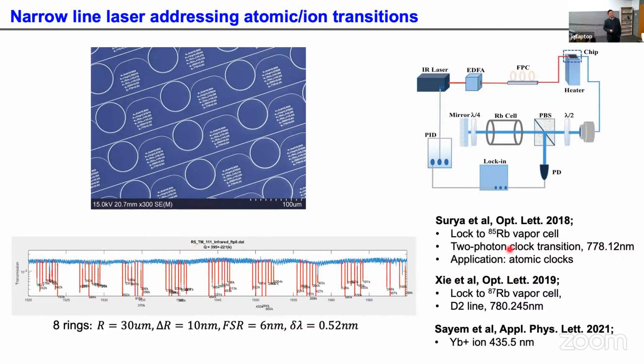One of the challenges in addressing these specific transitions is that you need to tune your resonator to exact wavelengths. Because those are resonant and Doppler-free, the phase matching window is pretty narrow, so you have to use device multiplexing. We have a device that has 16 resonators on a single pair of waveguides, so you have 16 resonances within a free spectral range. Here, the example I'm showing has 8 resonators on the pair of waveguides, so you have 8 resonances, and you can control each resonance very precisely. Each of these rings only varies in dimension by about 10 nanometers, either in radius or width, and you can hit the atomic transition. That's the idea for integrating with some of the clocks.